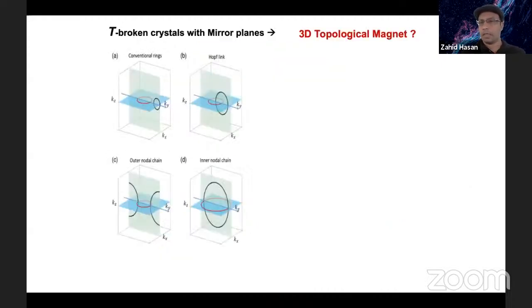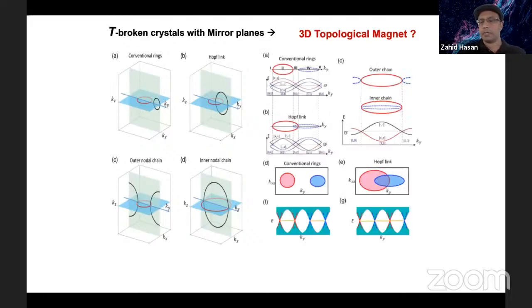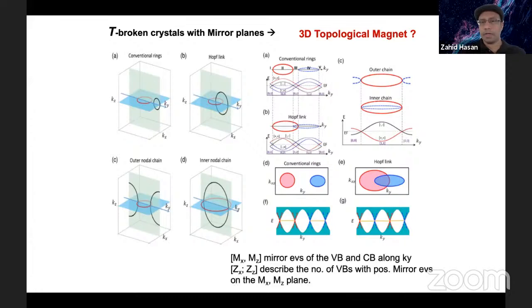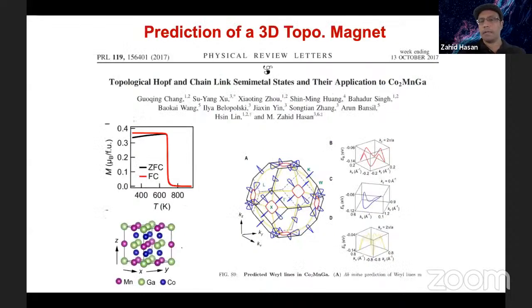So we use that idea to interlink those sorts of loops and look for materials where those links are protected by mirror symmetry or in the absence of time reversal invariance. By extending those ideas into these interlinked chain-link states, we searched the database to find a material where this type of thing will be realized. So this was our prediction of a 3D topological magnet, this cobalt manganese gallium system.